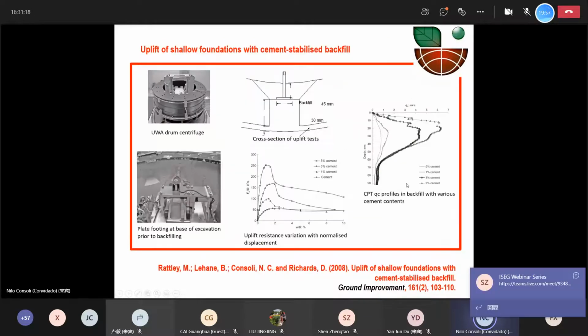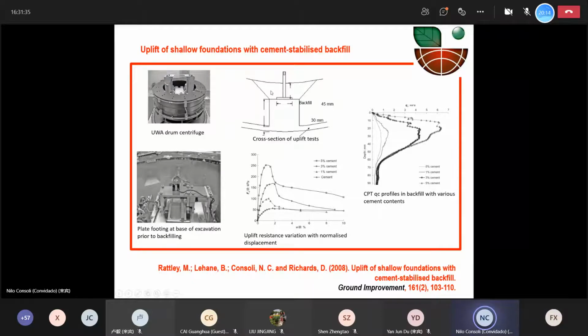And using, for example, this was a paper that was published in 2008 on the same concept of using cement, but in this case, we are going to put a shallow footing that is going to be pulled out. So instead of digging a hole here, putting the shallow footing and just inserting, for example, sand here, we put sand with some different amounts of cement, and we show that if we pull it out, this was carried out in a centrifuge at the University of Western Australia, where I have been for 1 year in one of my sabbatical licenses.